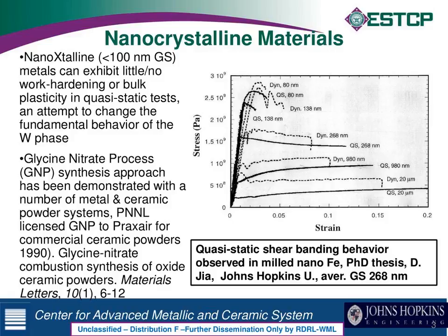And the illustration is in that plot there for just iron, pure iron, as you go from a grain size of 20 microns for the lowest curves. So the curves here are both the quasi-static curve, which is the solid line, and then the dash curve is the dynamic, again in a dynamic compression test, the split Hopkinson bar. And so as you refine the grain size from 20 microns, the two lowest lines, to 1 micron, it jumps up. You see the strength has gone up a lot. And then as you continue to refine the grain size, the strength continues to go up, but the shear band collapse suddenly appears in the nanocrystalline iron.